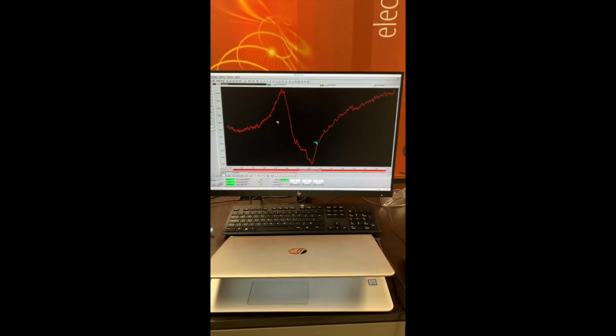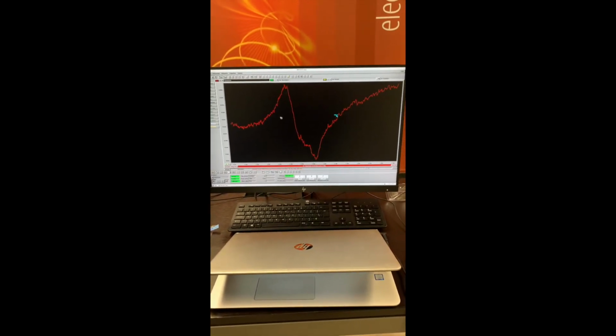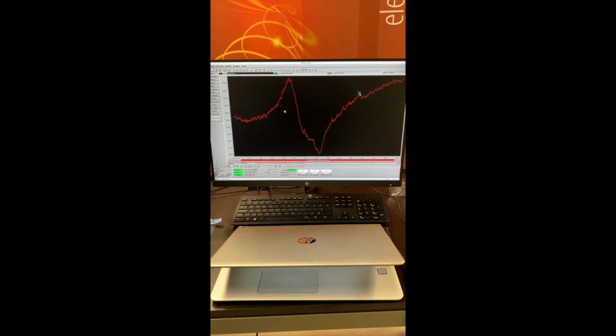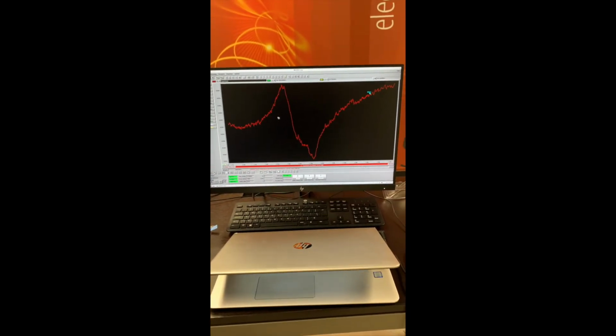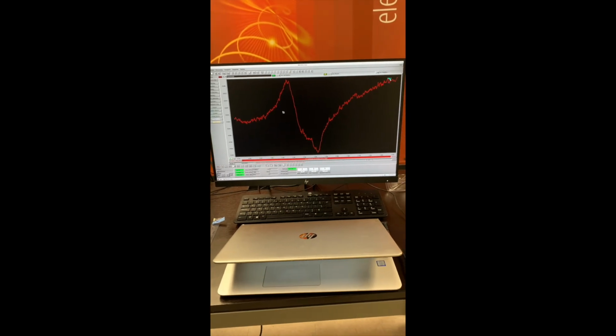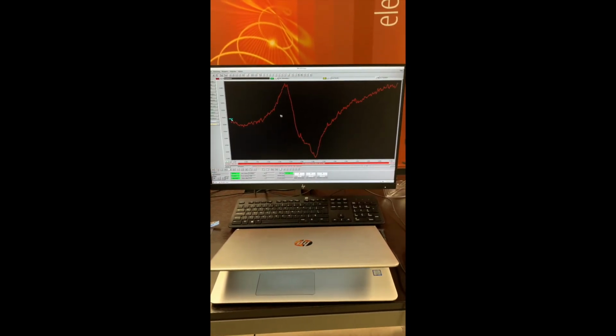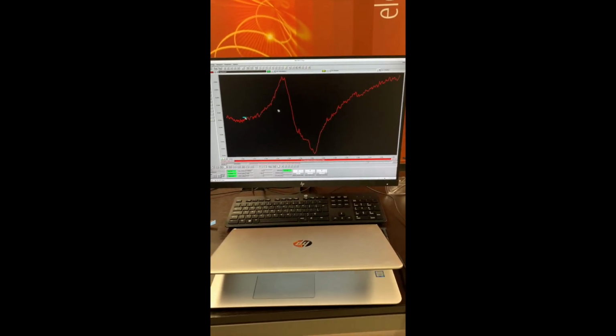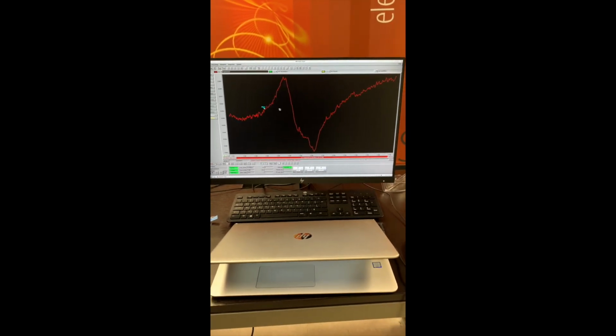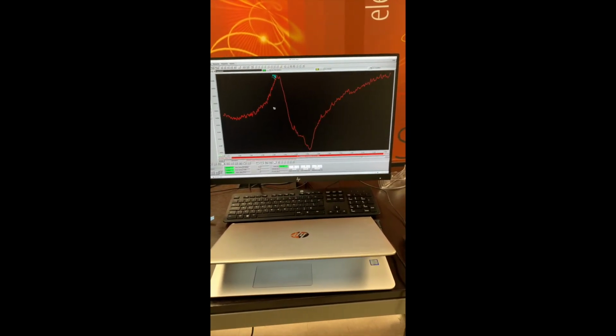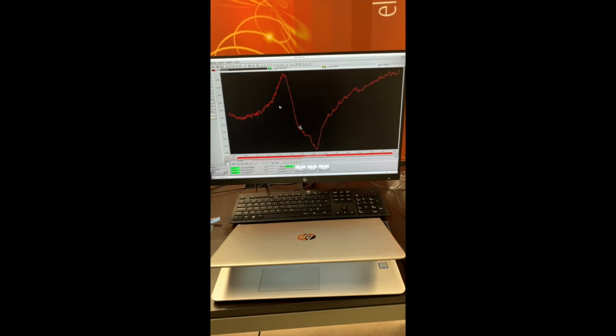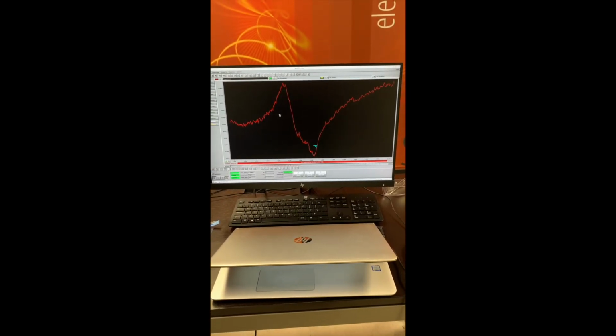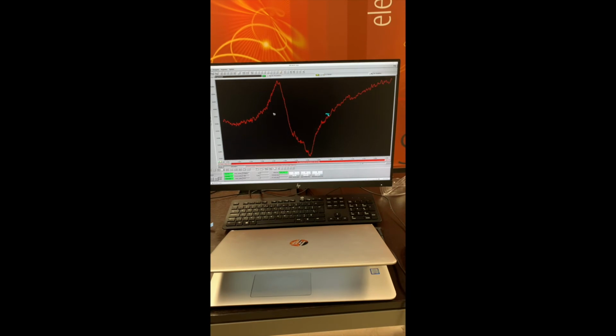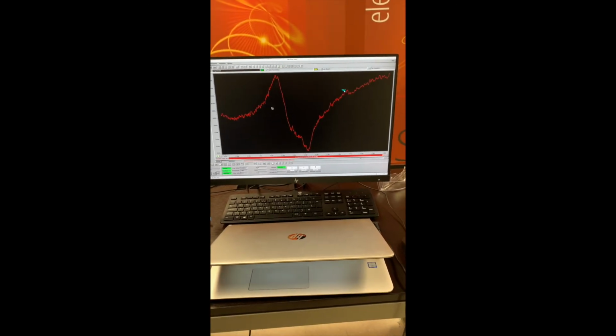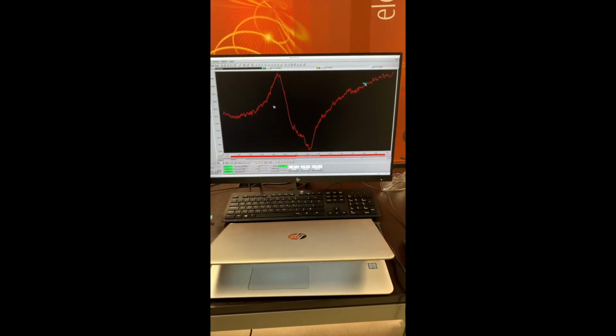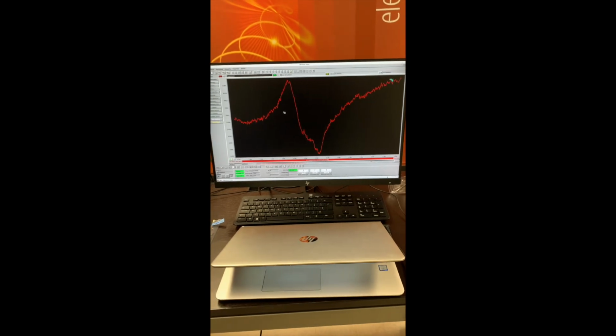We're plotting EPR intensity on the y-axis as a function of magnetic field on the x-axis. And we can see that there is an EPR signature characterized by an increase and a decrease in EPR intensity in the middle of the screen. And where the inflection point is, where the cursor is going through right about now, is called the g value. And that g value can tell us a lot about the electronic structure and the electronic environment of defects found in the crystalline silicon bulk.